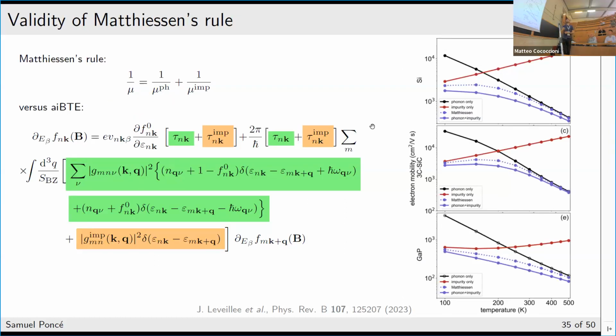One thing that is interesting is that we can assess the validity of the Matthiessen rule. The Matthiessen rule is extremely widely used, and it tells you that you can basically separate the phonon and the ionized impurity contributions. So you can say that the inverse mobility is equal to the sum of the inverse phonon-limited mobility and the inverse impurity-limited mobility. And so here you see the decomposition. This is the phonon-limited mobility. You remember, if you increase the temperature, the mobility is going down. Instead, if you increase the number of carriers, actually the mobility is going up. So this is the impurity-only term. And then if you use the Matthiessen rule, you get this dashed line.